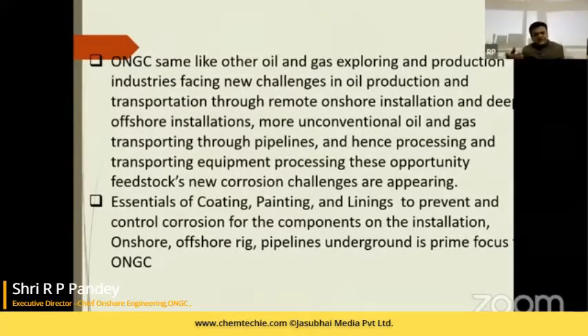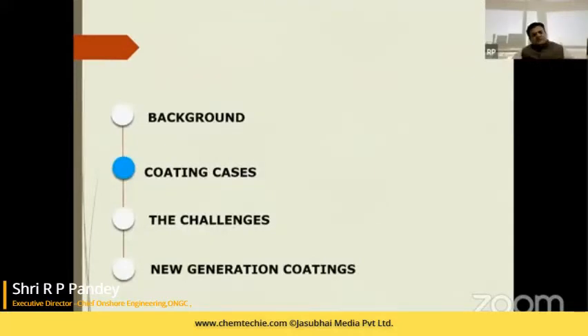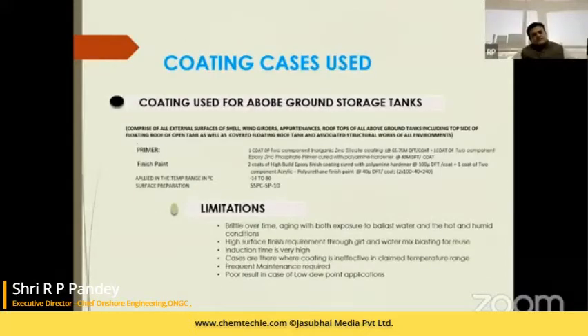The coating cases. For above ground storage tanks, we are using a coat of two-component inorganic zinc silicate at nearly 60 to 75 micron DFT, plus one coat of two-component epoxy zinc phosphate primer cured with polyamine hardener at 40 micron DFT per coat. Two coats of high build epoxy finish cured with polyamine hardener at 100 micron DFT per coat, plus one coat of two-component acrylic polyurethane finish paint at 40 micron DFT, coming to nearly 240 DFT in total. Our temperature range is minus 14 to 80 degrees and the surface preparation required is SSPC SP10.